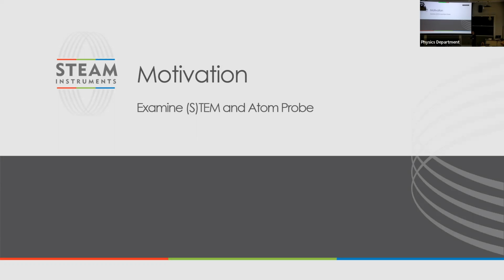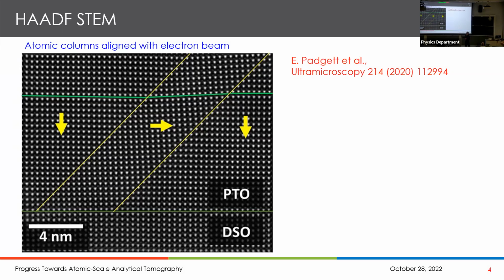And so I want to give you a little bit more motivation for why, and look at the role that scanning transmission electron microscopy, when I write this way, I mean either TEM or scanning TEM, and atom probe, how they can play together nicely. If you look at this image, what you may see is atoms, right? Lots of atoms. Well, actually, this is a high angle annular dark field image from a STEM. People in this audience probably know that those are not atoms, those are columns of atoms that we're imaging. They're probably about 50 atoms thick. So maybe 10,000 atoms in that image, or something like that. And what you see though is a lot of excellent detail, very high spatial fidelity, resolving the atomic lattice, even resolving this, which is a ferroelectric domain that is different in lead titanate deposited on dysprosium scandate, from this recent paper from the Cornell group.